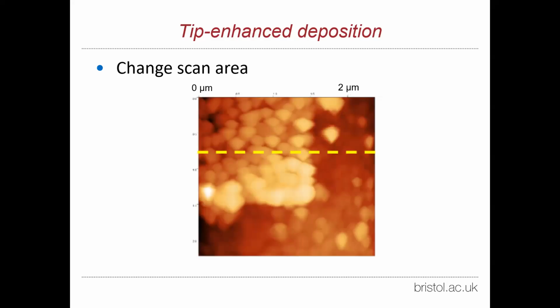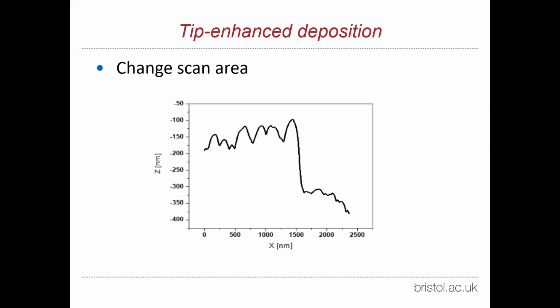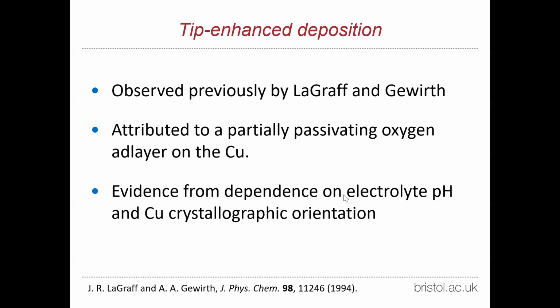One thing that we can do is we can see that if we move from this area to another area during the deposition, we see a square appear. What that means is that if we change the scan area, we are now moving from an area where deposition has taken place here to a deposition where it has not taken place. And the fact that we see a step tells us the deposition is fastest where the tip is scanning.